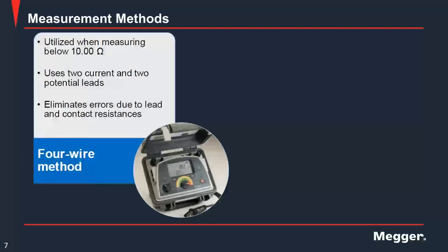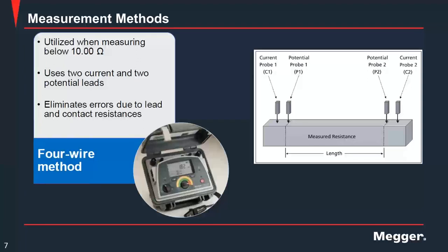And the last method that we know is the four-wire method. This method is used when we try to measure low resistance, or resistance below 10 ohm. The key aspect of this method is that we use two current probes and two potential probes, and this eliminates any error due to lead and contact resistance. So we want to eliminate any resistance measurement other than the test specimen. You can look at the picture on the right screen. There are two current probes, C1 and C2. And between the current probes, there are two potential probes, P1 and P2.